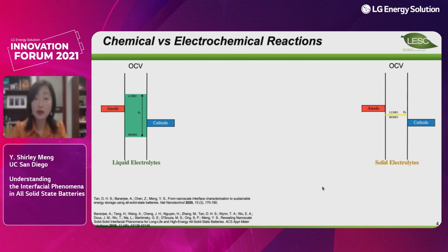So when we look at the difference between liquid and solid, one of the obvious differences we should understand is when we deal with intercalation chemistry, like graphite and LNMO or NMC or lithium cobalt oxide cathode, the electrolyte based on carbonate electrolyte is chemically stable. That means the HOMO-LUMO is actually outside the stability window.